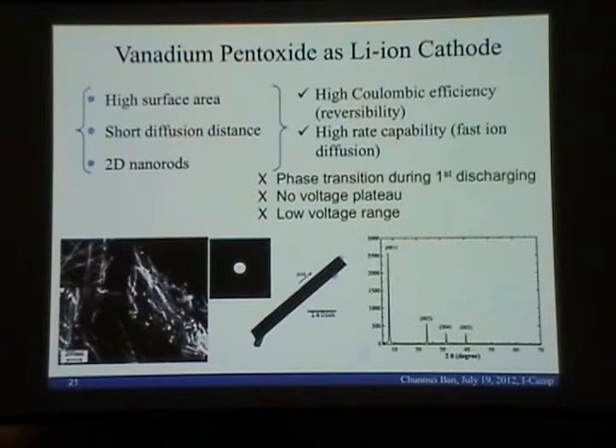The disadvantage of this kind of material is, first, the irreversible loss. As I mentioned, they have a phase change in the first lithiation. That means they need to use some lithium to finish this transition, and then some lithium will permanently locate in the structure and is not releasable. That gives the irreversible capacity. And the second one is a low voltage plateau.